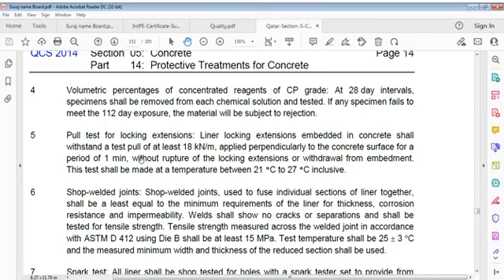So we got here volumetric percentages of concentrated reagents of CP grade at 28-day intervals. Specimen shall be removed from each chemical solution and tested.